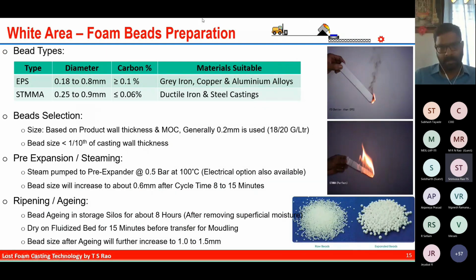The next one is the white area. The white area, which looks white, is the foam beads preparation. There are two significant foam beads available in the market today. The first one is EPS. The diameter of EPS varies from 0.18 to 0.8 millimeter. The carbon will be over 0.1%. It is suitable for gray iron, copper, and aluminum alloys. Similarly, STMMA: the size is a little larger and carbon is as low as 0.06. It is suitable for ductile iron and steel. Steel again is not stainless steel, because stainless steel is sensitive to carbon. We can make carbon steels in this process.